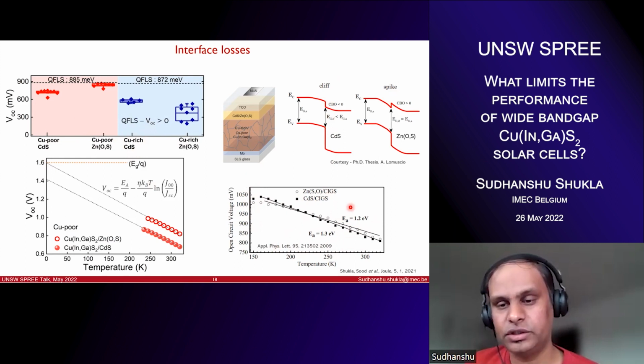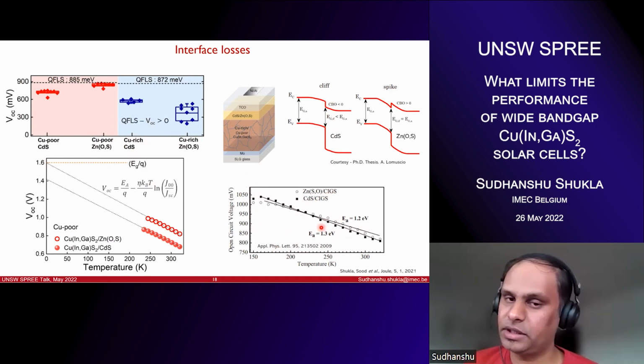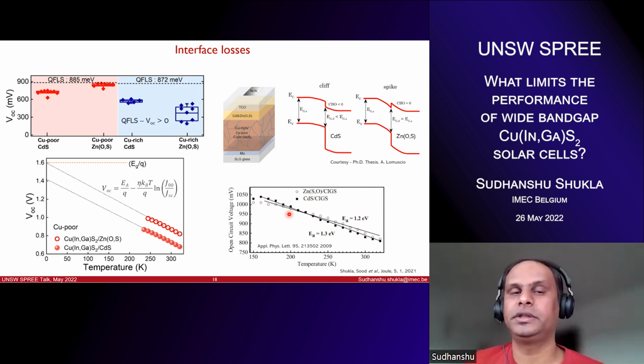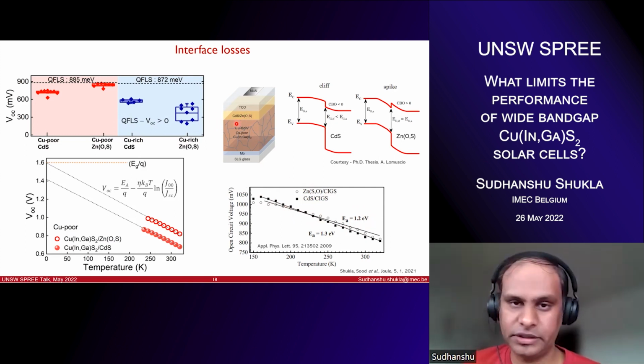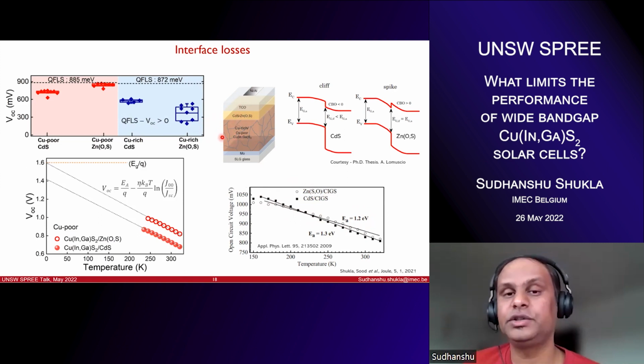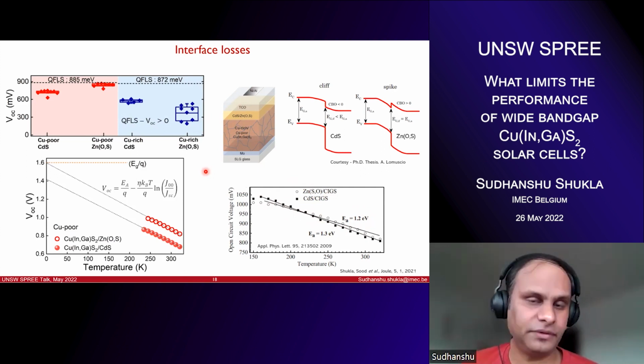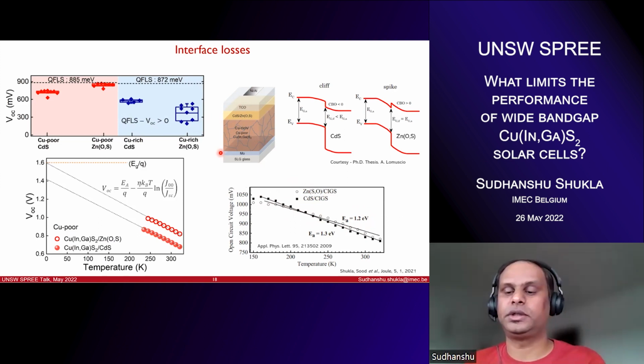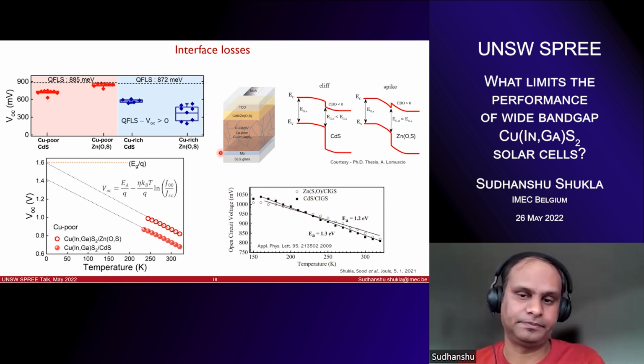So this plot that you see on the right bottom has been done on the copper-rich absorbers mostly. That's why the interface recombination limits this activation energy, so it doesn't go to the band gap. So the conclusion here is that if you want to passivate your interface by varying buffer layers, probably it will not passivate it unless you play with the stoichiometry of the absorber itself. So the passivation is composition dependent of the absorber itself, and it's most effective when you take copper-poor absorbers only.